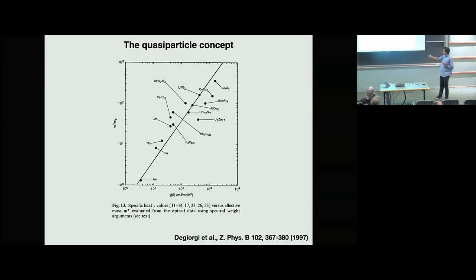To plot the data on the bottom, this is basically the heat capacity, so it's a measure of how energy is absorbed into a material. And on the vertical scale, a very different experiment where you're essentially measuring the inertia of systems, shaking charge carriers and seeing what their inertia is. And so it's a good plot because it illustrates something that we like to illustrate to students, and that's this notion of a quasiparticle, that despite interactions, electron-electron, electron-phonon, electron interactions with local moments, all of this kind of conspires to give us, in the end, in situations like this, renormalized quasiparticles, but nevertheless renormalized quasiparticles.